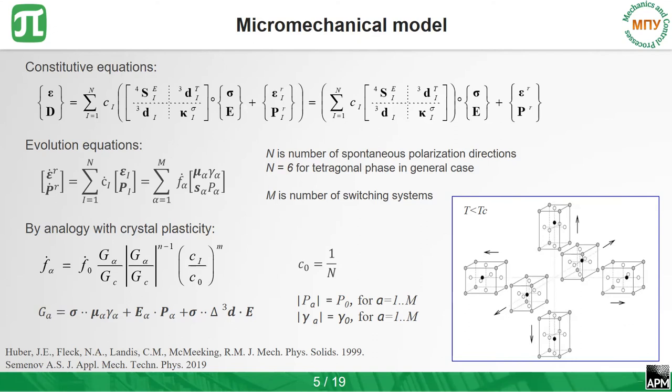So the main idea is that if we have a tetragonal ferroelectric under the Curie temperature, as for example barium titanate, it has six spontaneous directions of polarization. So we can write the constitutive equations as if we have six domains with six directions, which are defined by the volume fraction, c_i, the volume fraction. So we can write the constitutive equations for the whole material,